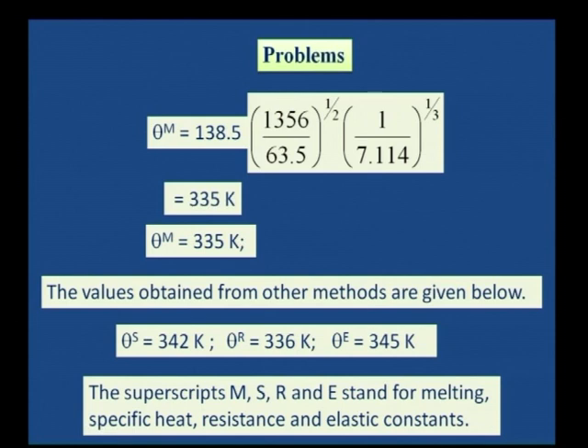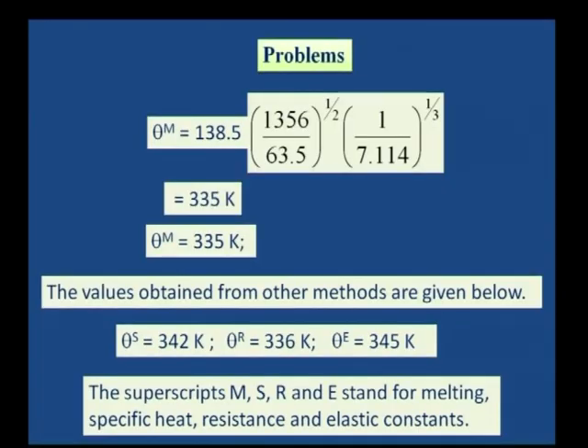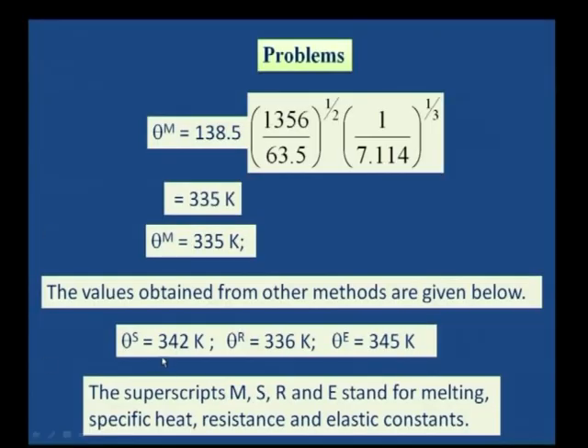Actually, the Debye temperature came into existence in the study of specific heats. Now, R stands for resistivity. I told you the Debye temperature is connected to electrical resistance. E refers to elastic constants. So, the Debye temperature is related to very many other phenomena. Therefore, the Debye temperature according to specific heat is 342, according to the Lindemann rule of melting it is 335. From resistivity data you get 336 Kelvin, and the elastic constant gives 345 Kelvin.